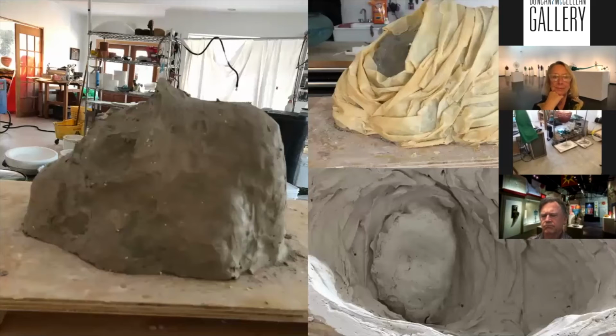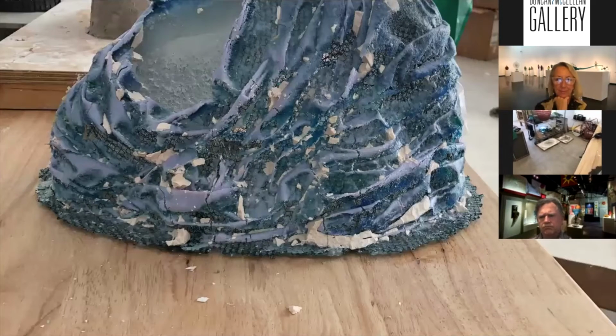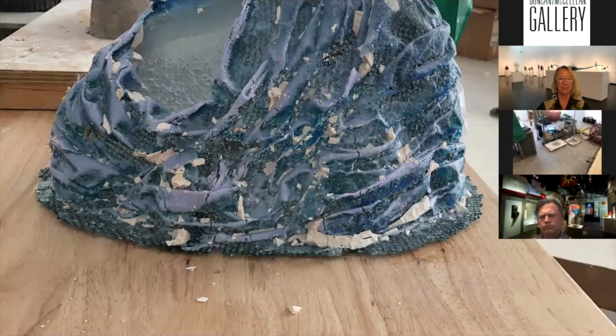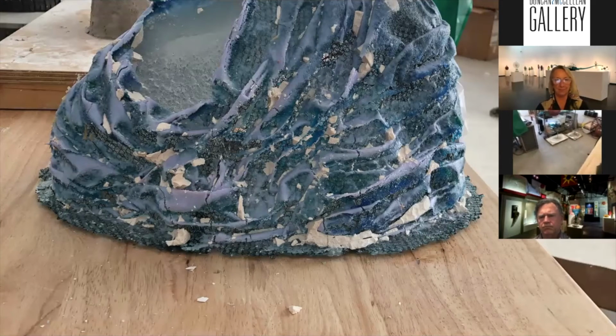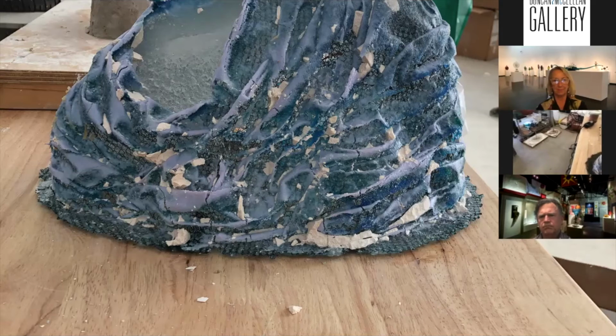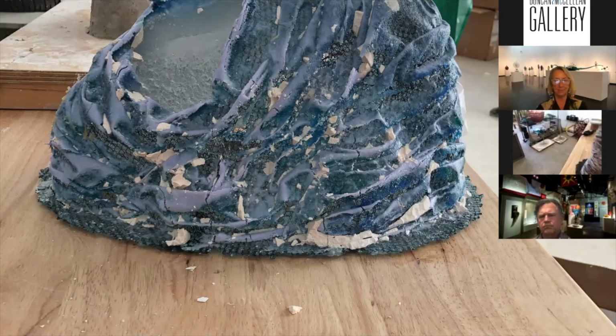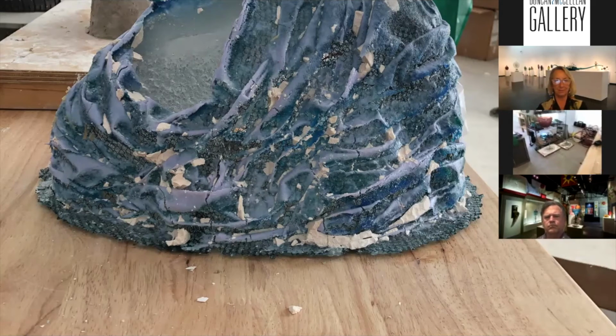Again, you can see there's a lot of challenges to get the glass to stay in that shape. So here I did my layers of colors, and then I put in the copper mesh, and then I have to do a thick layer of clear. That white glass is actually clear glass that I'm putting in there fairly thick and slowly building it up the sides. And that will go into the kiln and get fired. Now this image has just come out of the kiln and I broke the mold off of it. It still has mold material on there. So I cleaned it up, and then it's going to go in the electroplater for several days.